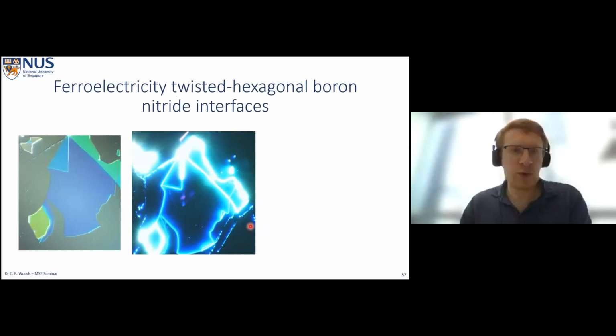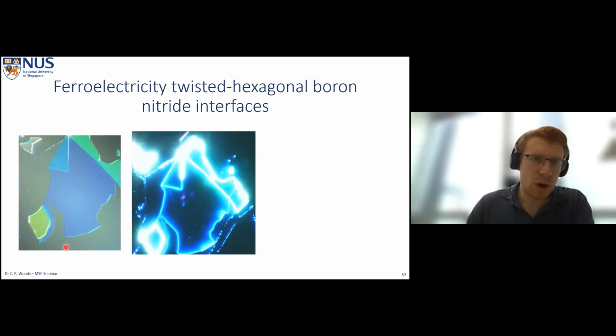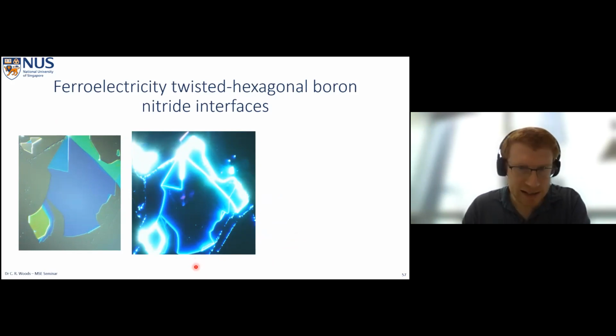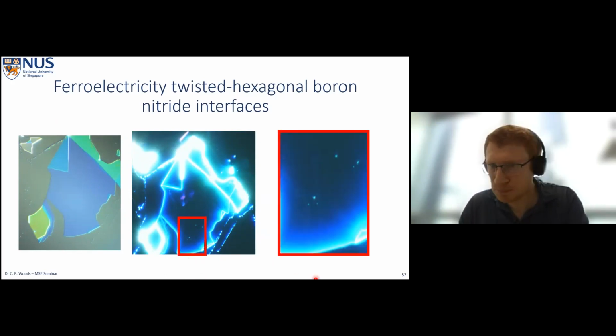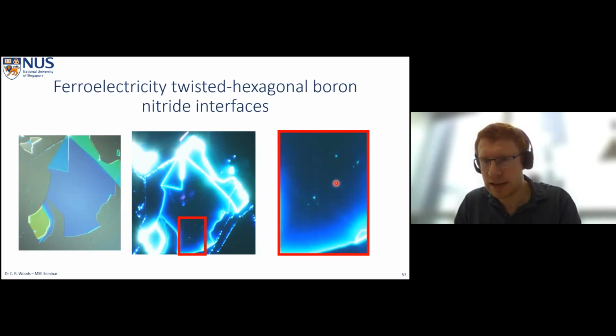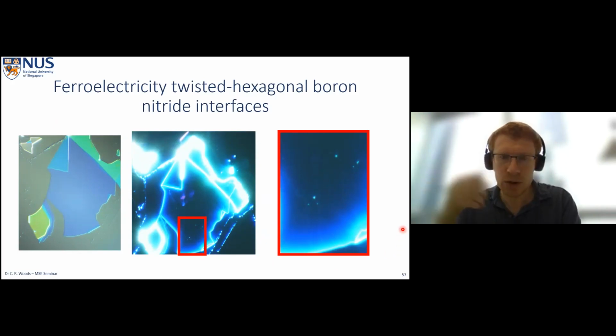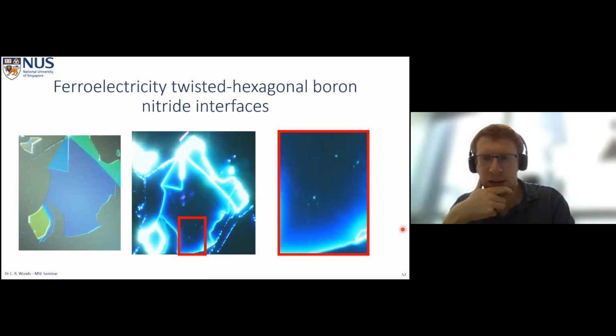Okay, so we produce samples like this. This is a bulk boron nitride crystal, and we're looking for a monolayer terrace in the interface here. I don't expect you to be able to see it, but just for your information, they're quite hard to find. There is actually one here, and it's down there. And maybe if I show you the dark field image, you can just about see that there's some scattering from this terrace here. So these are really hard to find, but not impossible. And yeah, that's where it is.